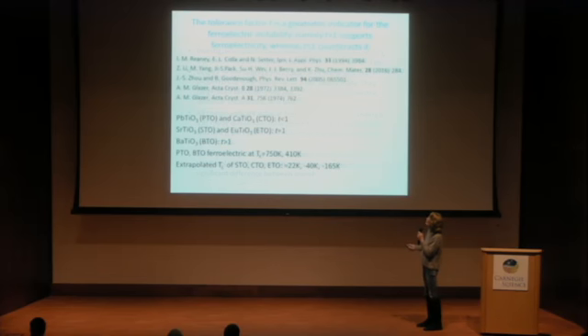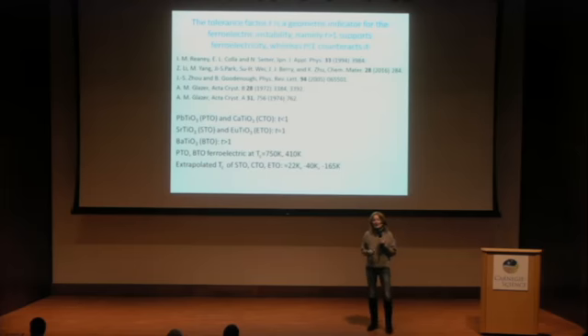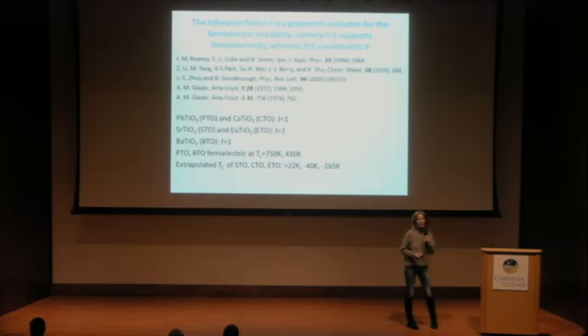And typically, there are many approaches like that, but the simplest one is based on Goldschmidt, Goodenough, Glazer, and all these people, who say the tolerance factor is a decisive quantity to differentiate between the ground state properties. The tolerance factor is familiar to all of you, and in its simplest form, it says if the tolerance factor is less than or equal to 1, the system should be stable and not undergo a ferroelectric instability. However, if the tolerance factor is bigger than 1, it is expected that the system undergoes a polar instability.